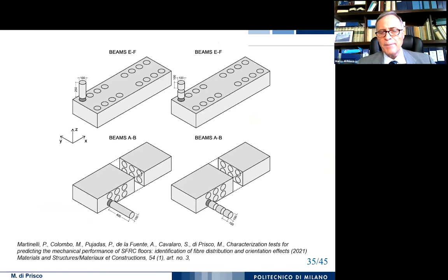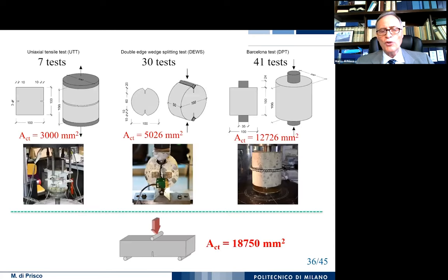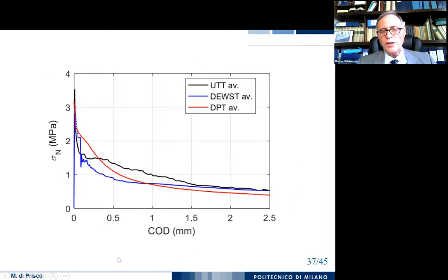And with the help of the Barcelona group, we cored in different positions and according to different directions. And what we saw is that if we compare the uniaxial tensile test on the specimens obtained by this coring, the double edge wedge splitting test and the double punch test, so different ways to obtain the uniaxial tensile response, we arrived with different areas of material subjected to uniaxial tension compared to the conventional test used for the classification. So you see which is the difference in the average between the three different types of tests that we can use to verify the behavior of our material.